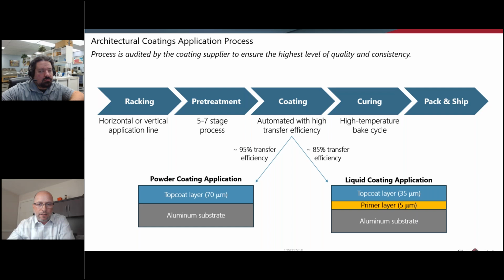When you talk about a liquid coating application, it's almost always using a primer, and the primer layer is about 5 microns, so a very thin film of a primer to help with corrosion resistance and adhesion. And then your liquid coating application top coat is about 35 microns. So overall, even though it's 2 layers, that's almost half the film build that you'll get with a powder coating.